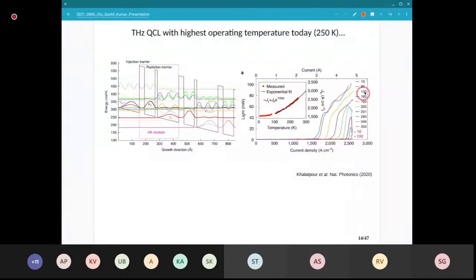These are the curves measured at different temperatures. What you can see is that they have the highest power output, about 100 milliwatts at 10 Kelvin, and as you keep increasing the temperature, the power drops. Now this is a Fabry-Perot laser. It has a horrible beam. I'll show you a little later. So this is by no means ideal.